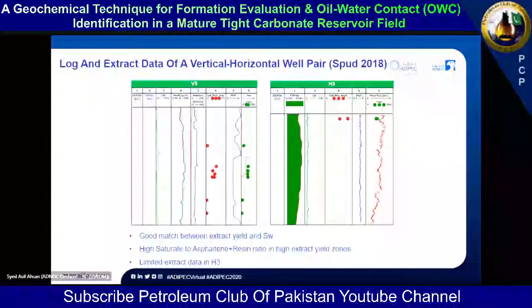V5 and H3, both wells were drilled in the low case, as you may recall the location of these wells. And you see that, again, the water saturation is matching nicely. The dense zone above is showing low extract yield, and the samples coming from the free water level are showing low extract yield. The horizontal hole, although unfortunately we didn't have many samples across the horizontal length of the well, but only one sample, in fact two samples, which are coming from very nearby depths, are matching nicely to the water saturation in this case.